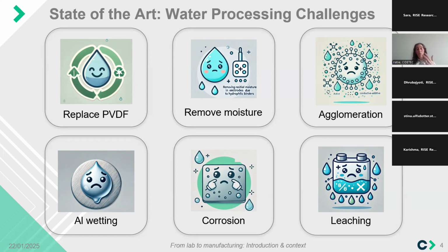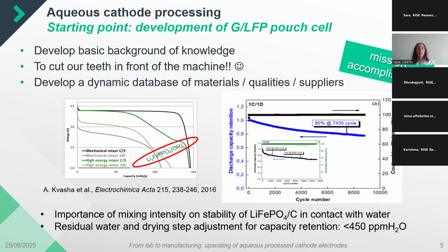Because it evolves when reacting with the aluminum, it creates a passive aluminum oxide on the surface, which reduces the performance of the overall electrode, but it also generates hydrogen that can evaporate - this is also related to the corrosion issue.